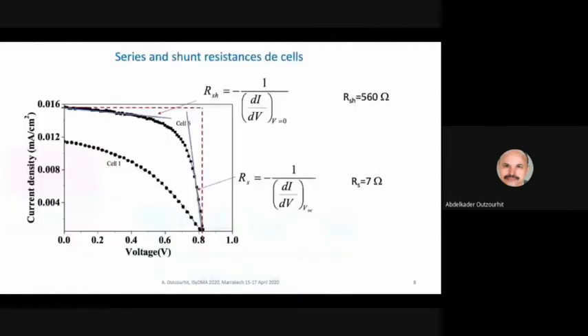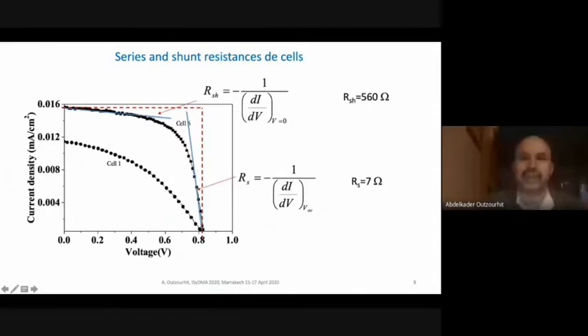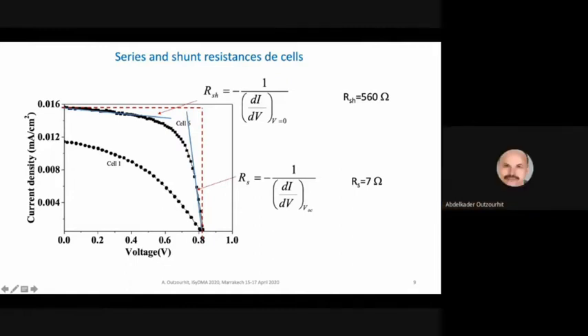So we used the current voltage characteristic of our cell to determine the shunt resistance, which is the inverse of the slope of this line at the short circuit conditions. And we also determined the series resistance of the cell, which is the negative inverse of the slope of this line at the open circuit condition, at VOC. We obtained a shunt resistance of about 560 ohms for the best cell, and a series resistance of about 7 ohms.